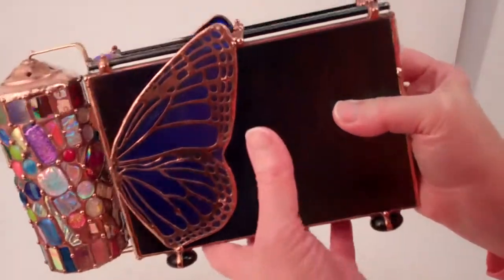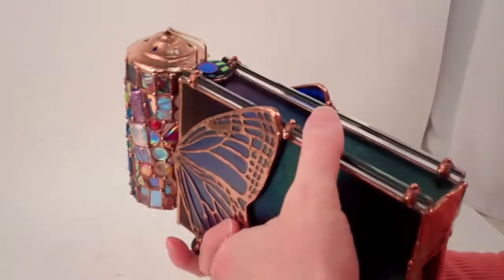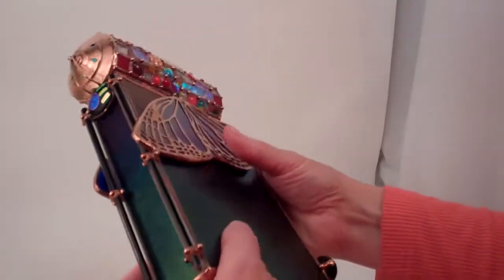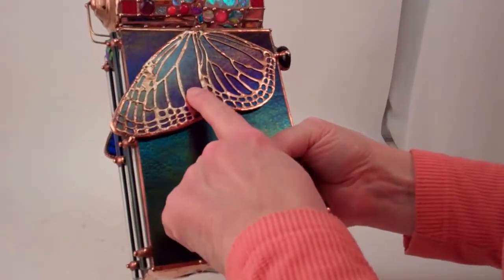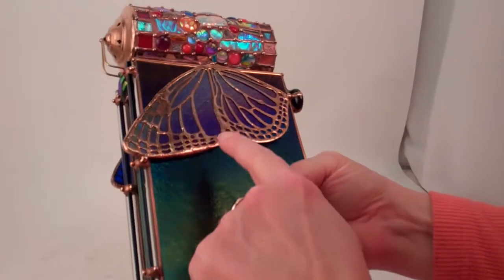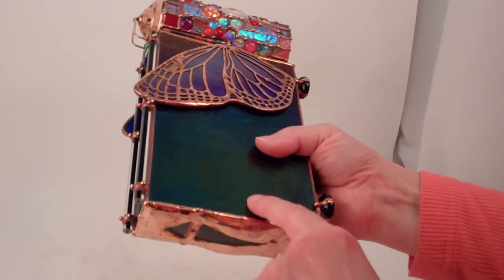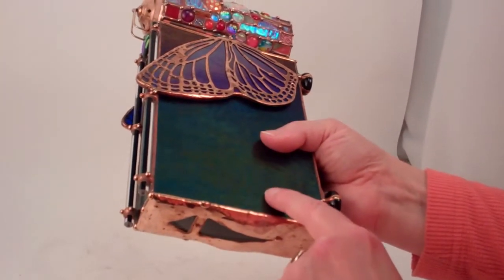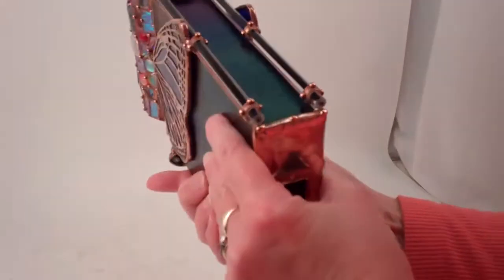The main panels on the kaleidoscope are black iridized glass, so they also have a sheen, but it's a different technique. Dichroic glass is vacuum plated metals directly onto stained glass, and iridized glass is stained glass that has metallic salts simply sprayed on them before they have annealed and cooled.